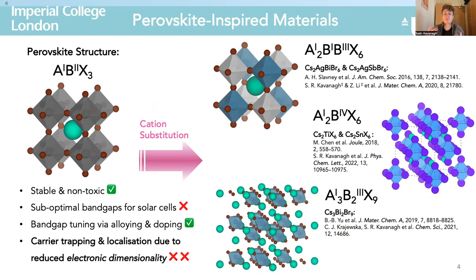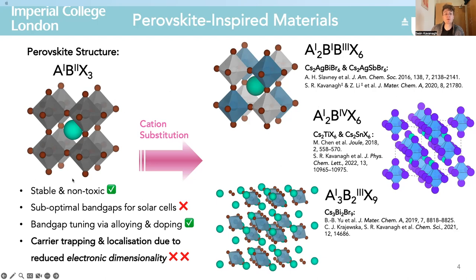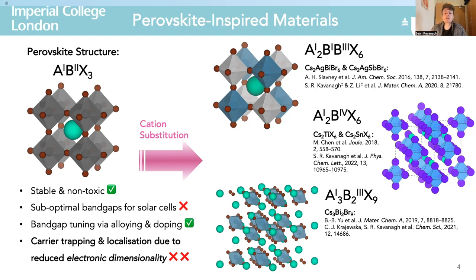One of the first materials design approaches used, and in fact probably one of the oldest tuning techniques in the chemist's toolbox, was that of atomic substitution. Here we retain the perovskite crystal structure but employ ionic substitution to replace our divalent B-site cation — i.e. lead — for a chemically similar species to avoid the presence of lead. However, a consequence of this cation substitution which has become clearer with more research is that it leads to a significant reduction in the electronic dimensionality of these materials.